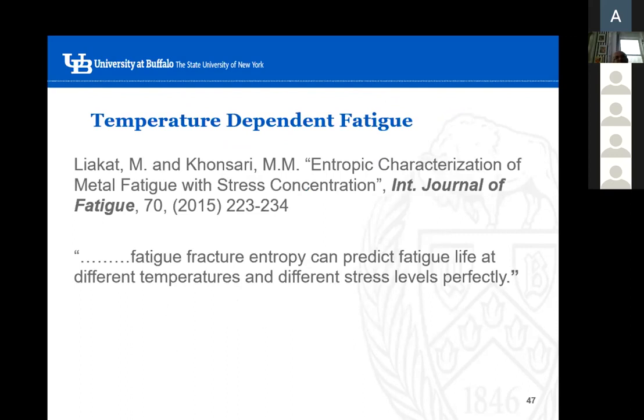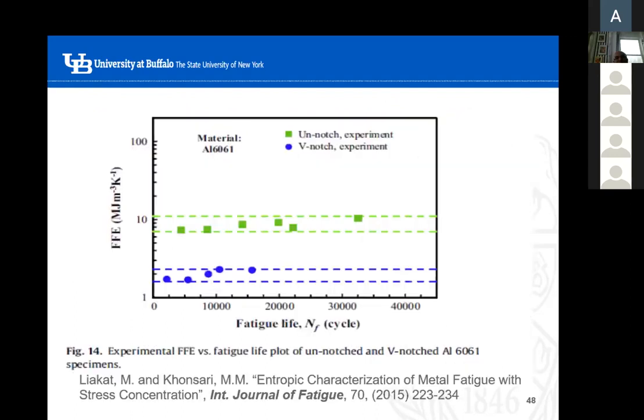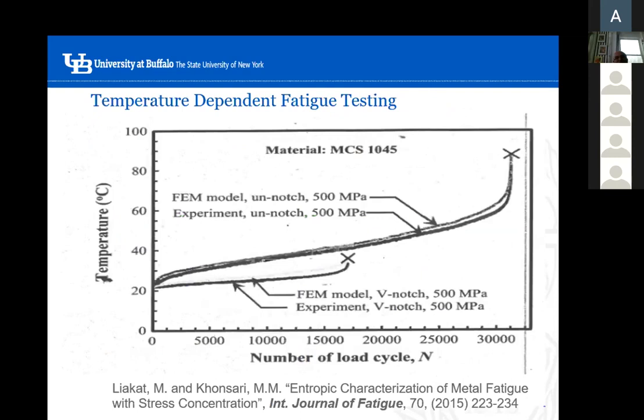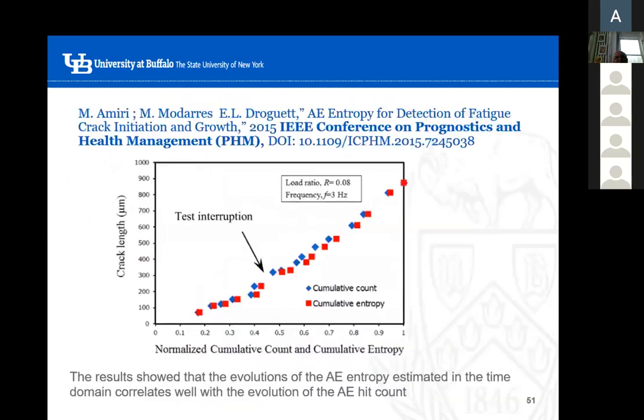And then this is another paper from Khonsari's group. Another result. Okay, so these are all the same. This one is again showing the crack length versus the normalized cumulative entropy. So essentially, this is more like fracture mechanics. For a given crack length, the required entropy to reach it. And then the cumulative count, which comes from the test data, and then this is the entropy for load ratio R 0.08 and frequency 3 Hertz.